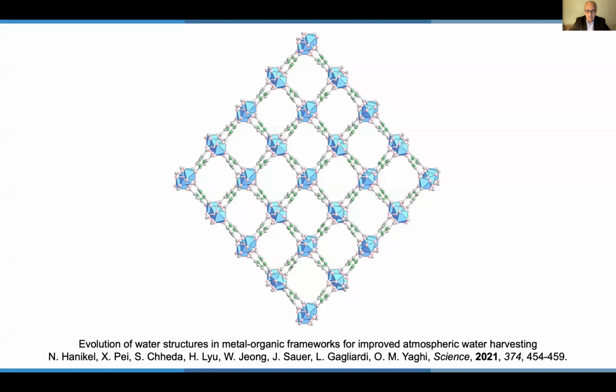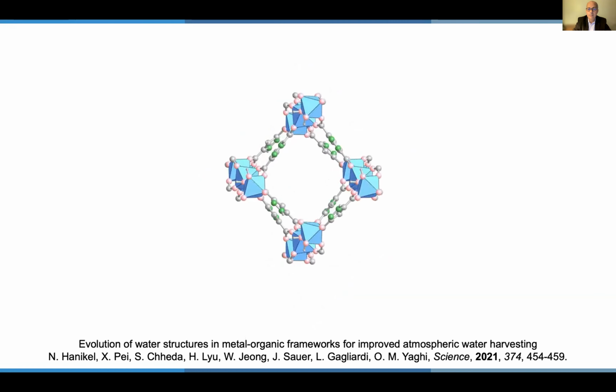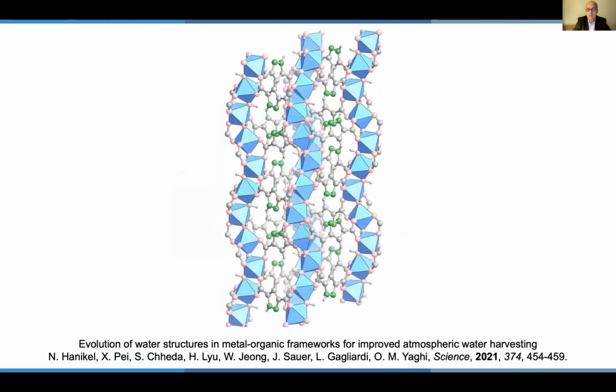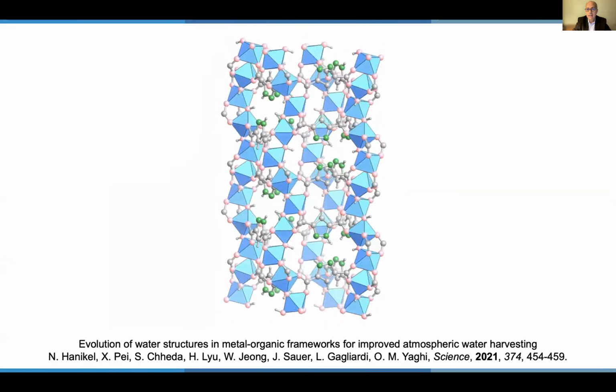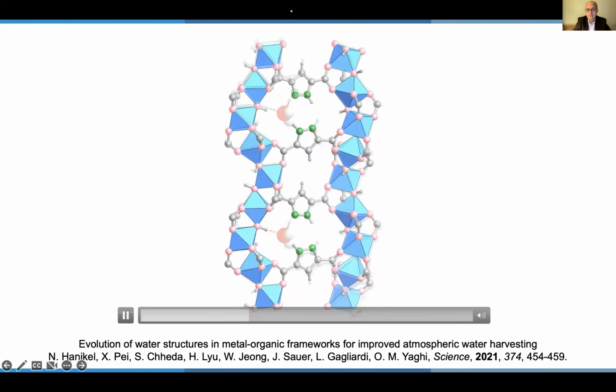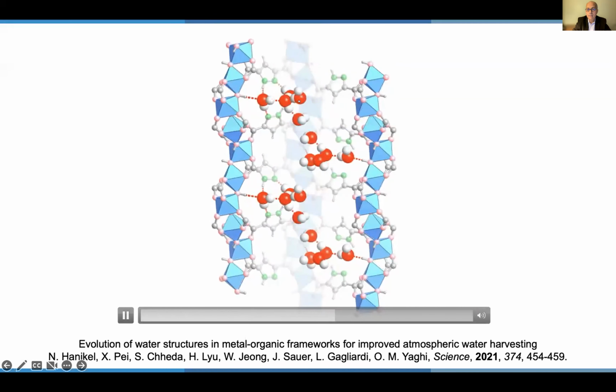more energy efficient materials. So this is, for those who are familiar with chemistry, these are illustrations based on single crystal X-ray diffraction data. It's the most definitive way of figuring out the positions of any molecule. So this is a video that shows the one pore, and we're going to cleave that pore so that you can see where the water molecules go. They first go to the hydrophilic sites, the nitrogen molecules of the linker, and then once those sites are filled, they bind through hydrogen bonding across a hydrophobic pocket.